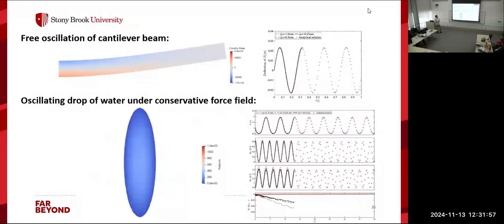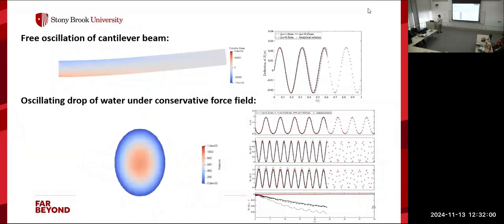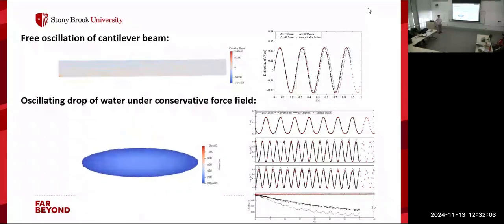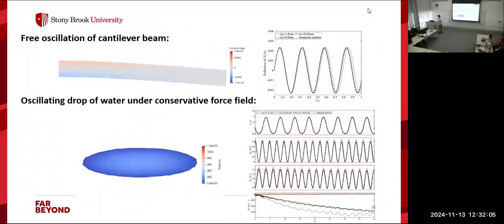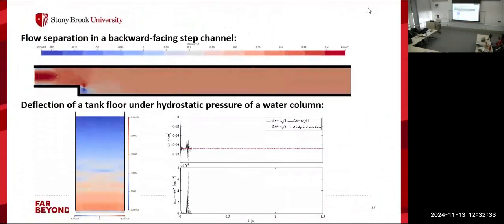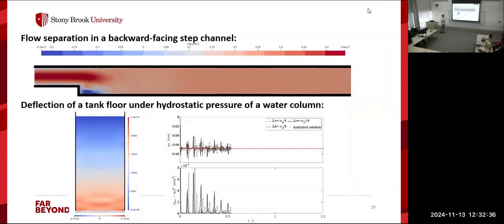So we first applied our method on simple structures. This is a free oscillating beam under a very simple initial velocity. We are tracking the tip displacement, and you see how the tip displacement is in good agreement with the analytical solution. And here is a drop oscillating under a conservative force field, and you see how the predicted results are in good agreement with analytical ones. After this, we moved on to apply our method to a more complex case.